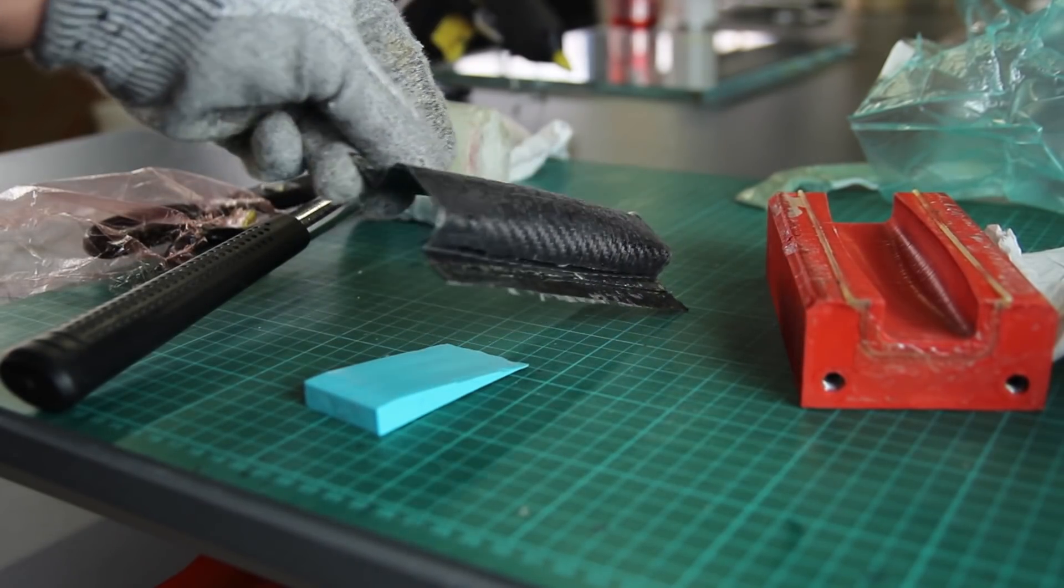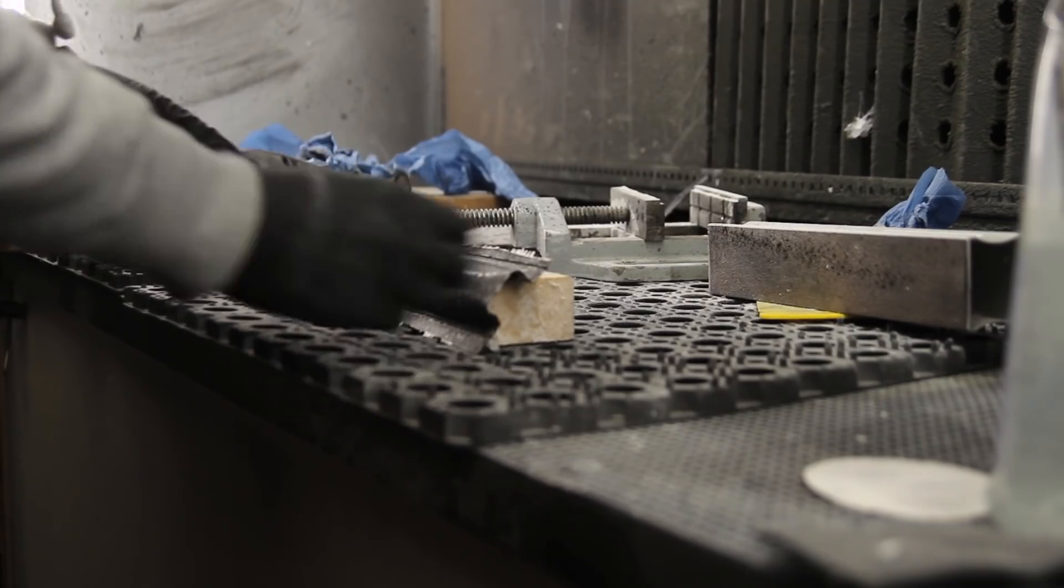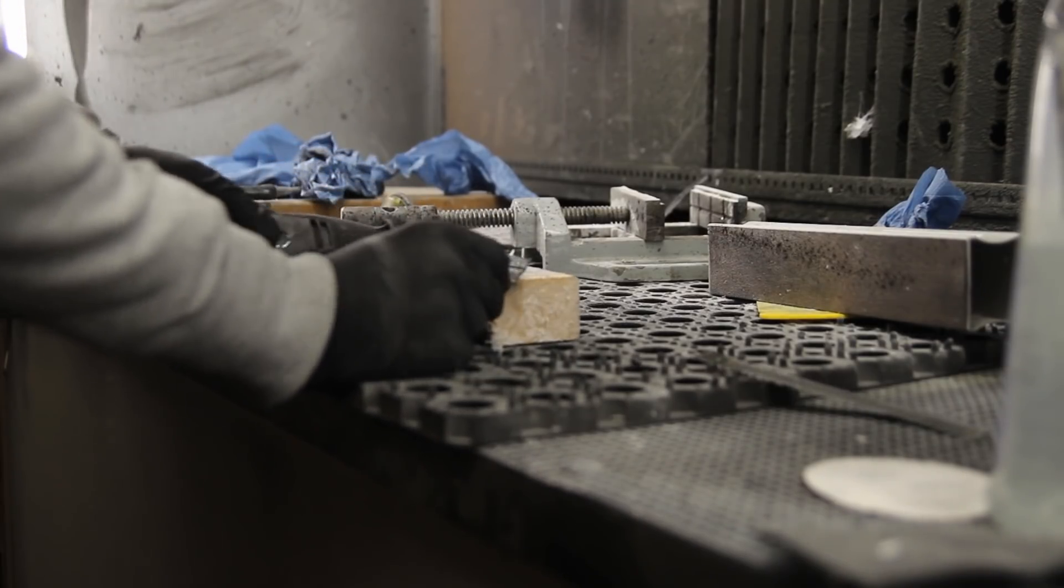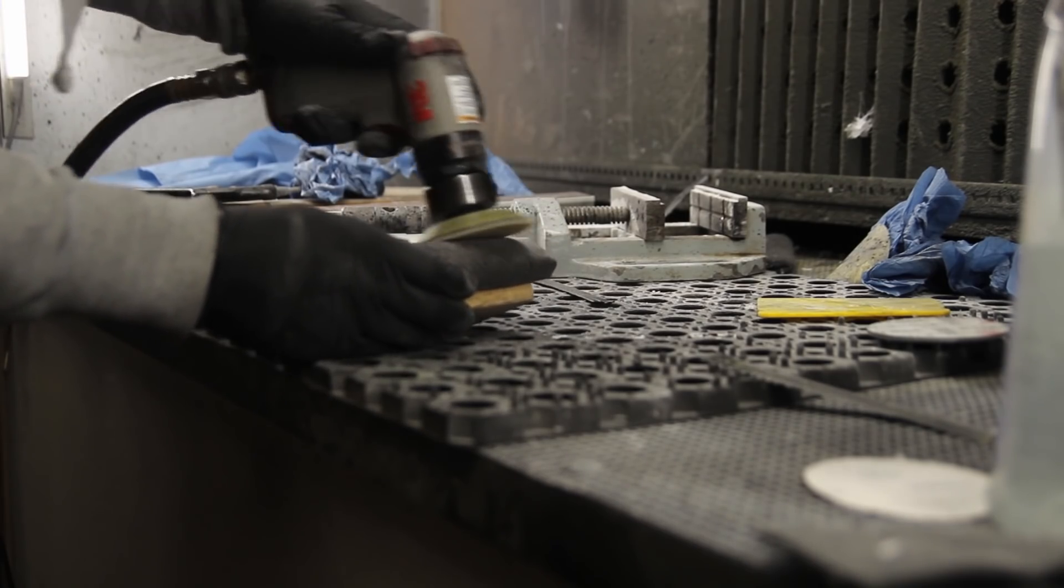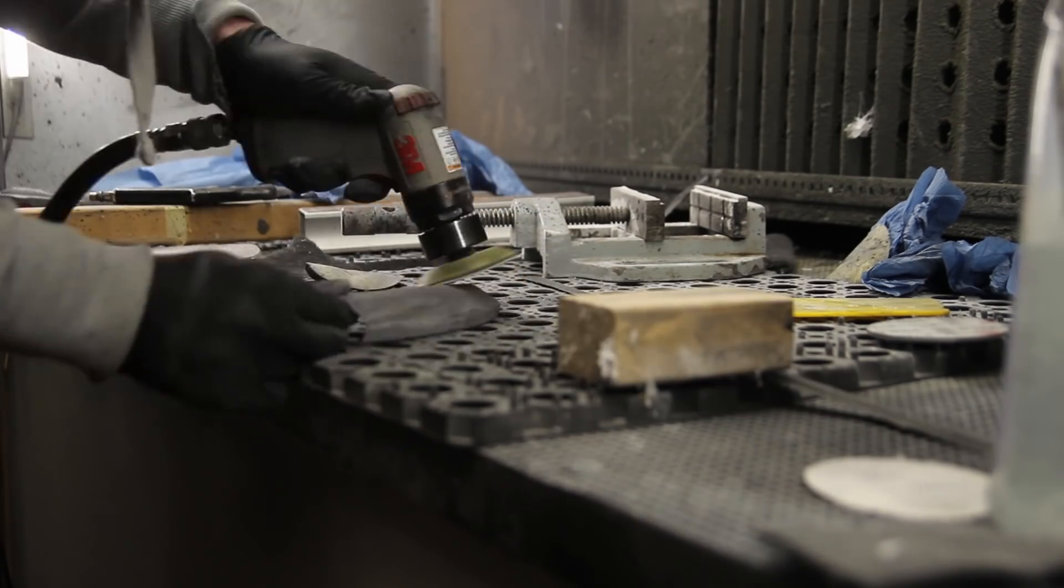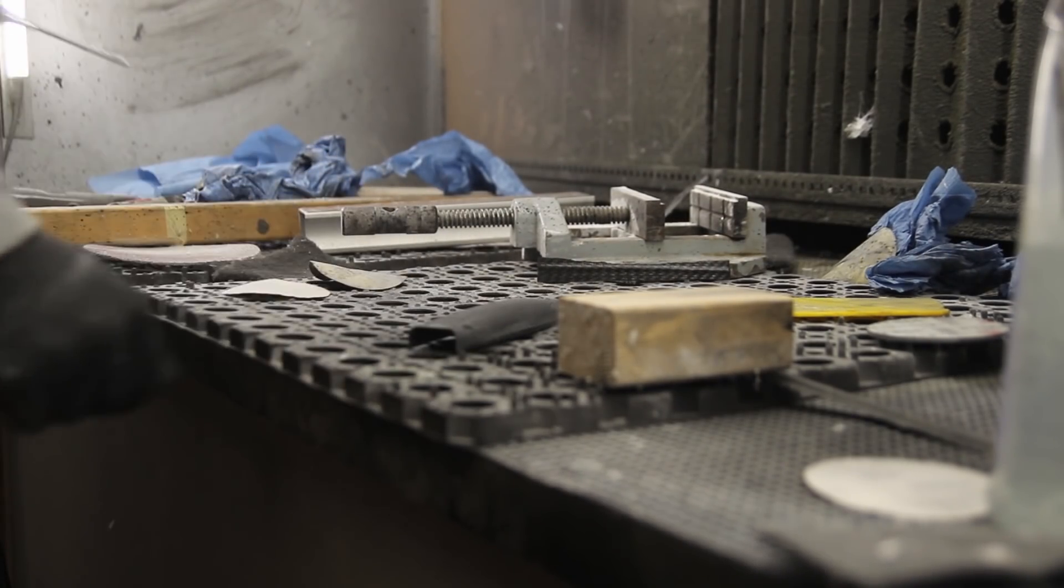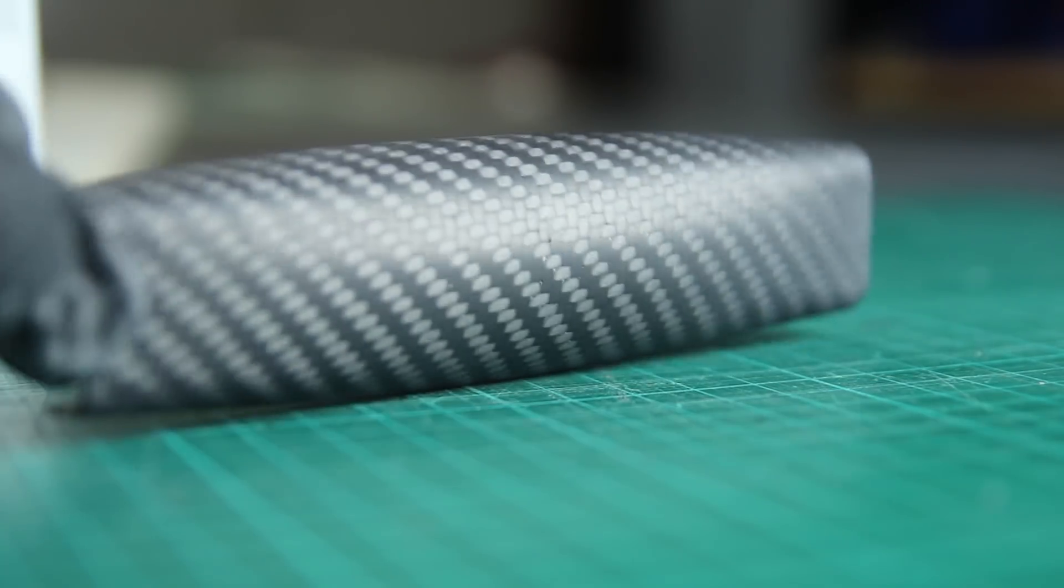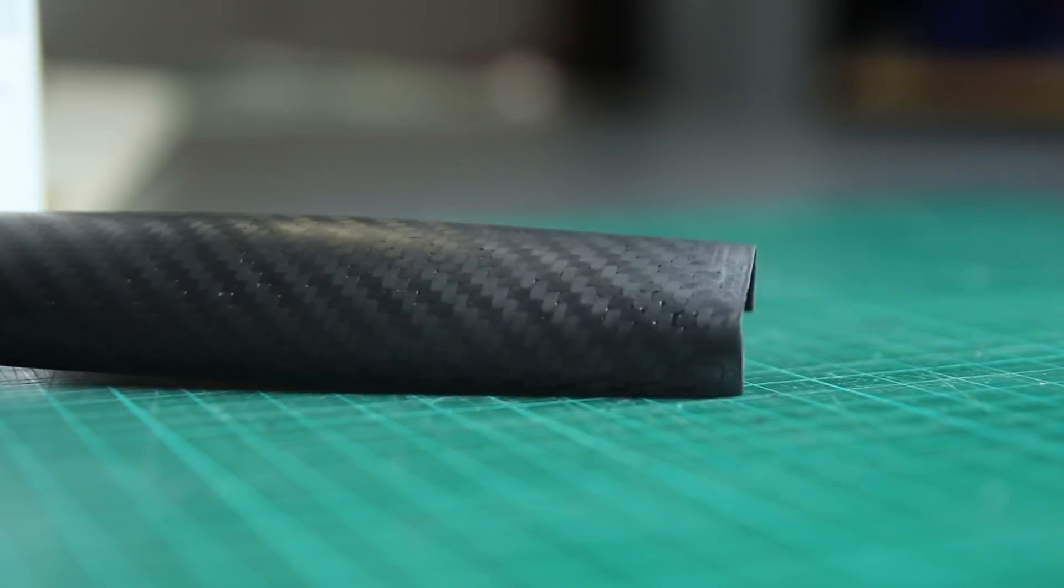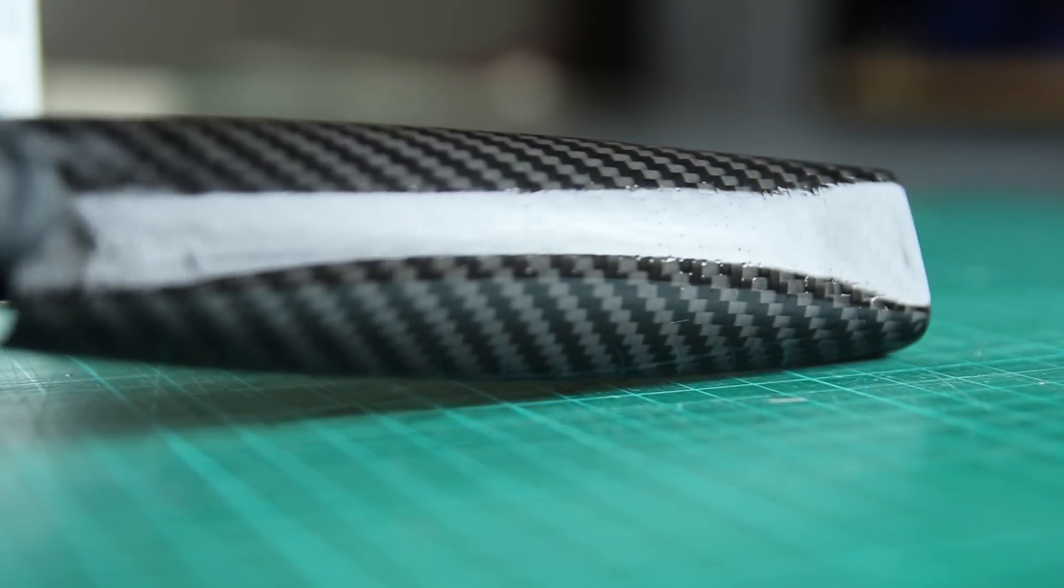Here we can see the results. We have some pinholes and some air voids, but seeing the geometry of the parts and where the air pockets are, I think it's more of a user error because I went quite quickly because I thought it was an easy shape. It's possible that I had some bridging there because the rest of the part is quite good. For the pinholes it's a problem, but this can be a curing cycle that isn't good. Other options are that the mold is outgassing something, like you have with polyurethane or polyester molds with prepreg causing some problems with the curing.